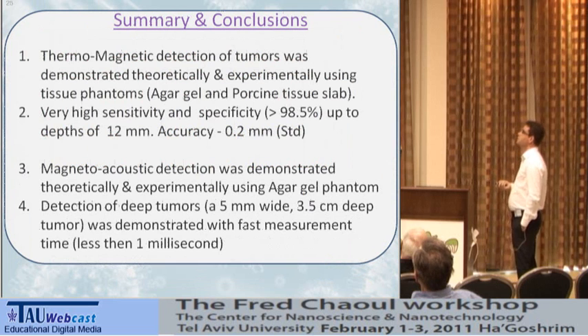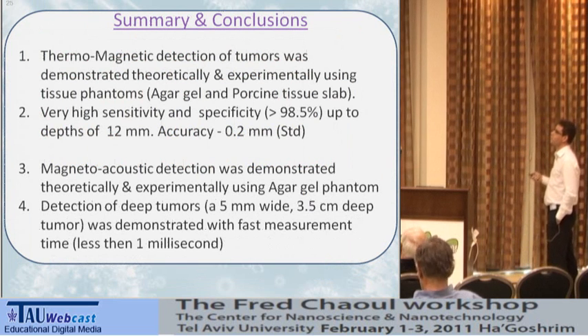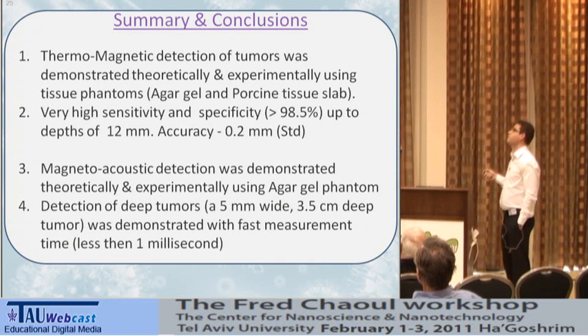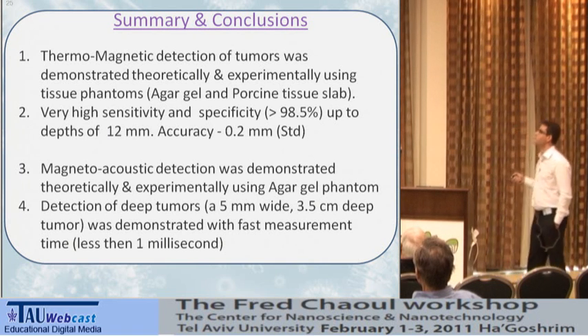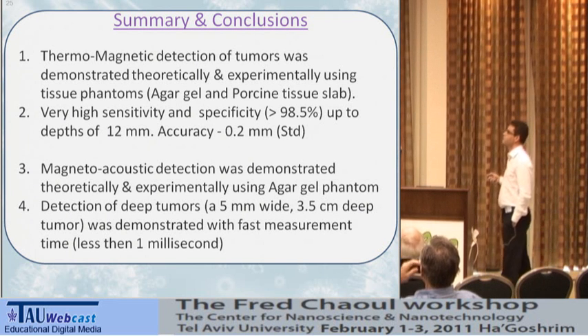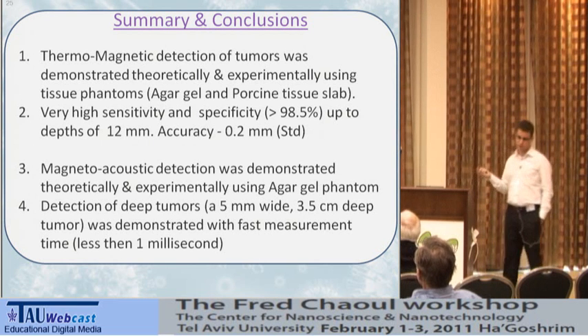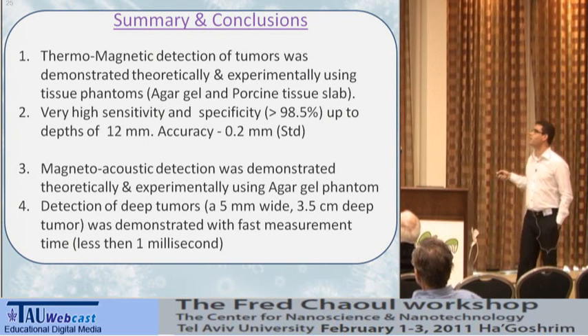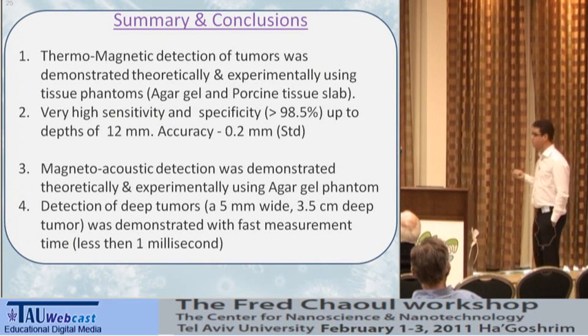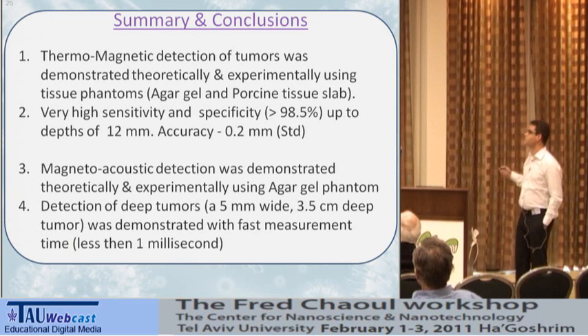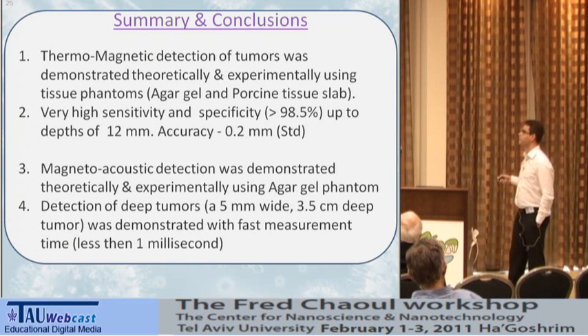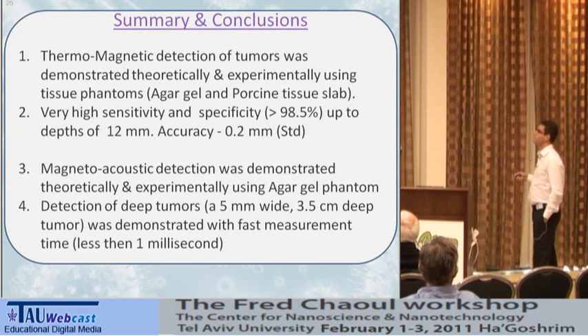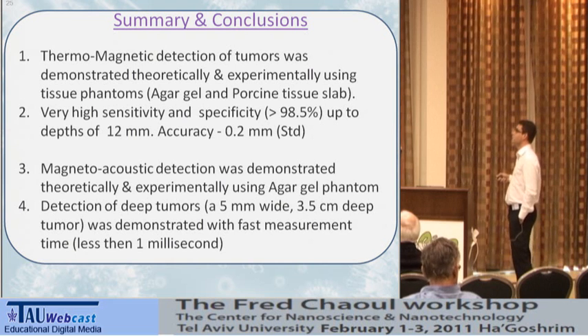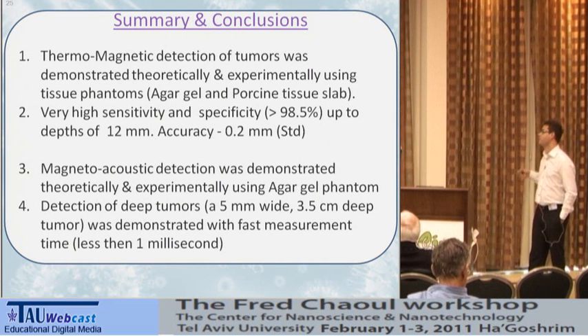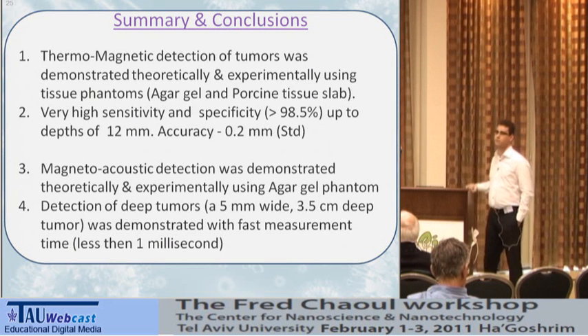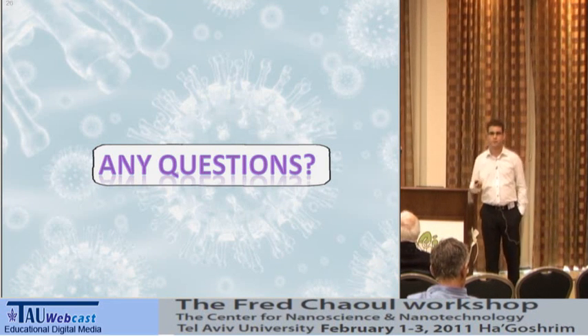It's very deep. So to conclude, we showed thermomagnetic detection, demonstrated theoretically and experimentally using tissue phantoms. We saw very high sensitivity and specificity, a depth of 12 or 13 millimeters, and also very high accuracy. The problem was with measurement times. So we did a magneto-acoustic detection. Also, we demonstrated it theoretically and experimentally. This time we used an agar gel phantom, and we demonstrated detection of a 5 millimeter wide, 3.5 centimeter deep tumor very fast, in less than 1 millisecond. That's it. Any questions?